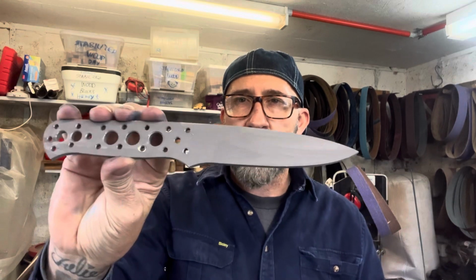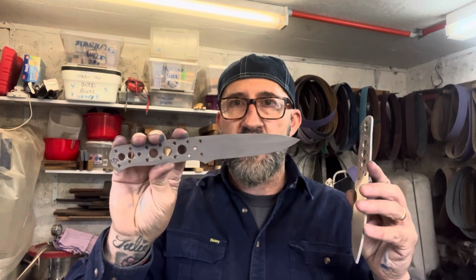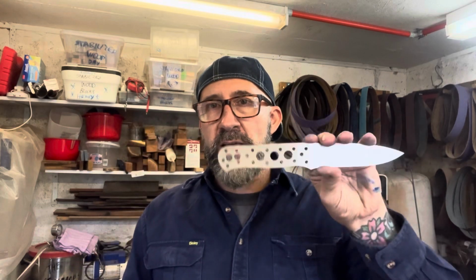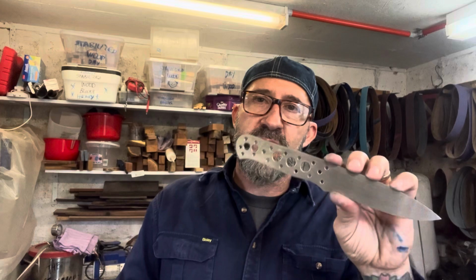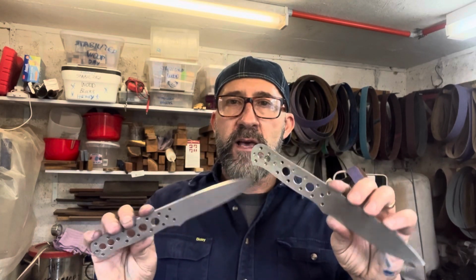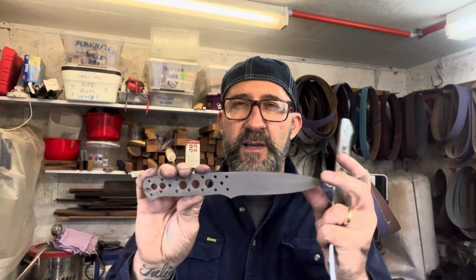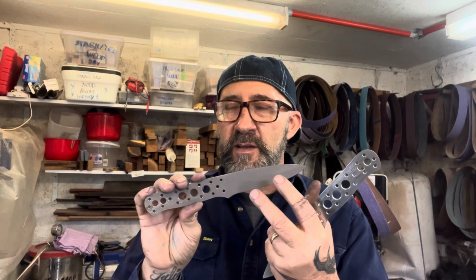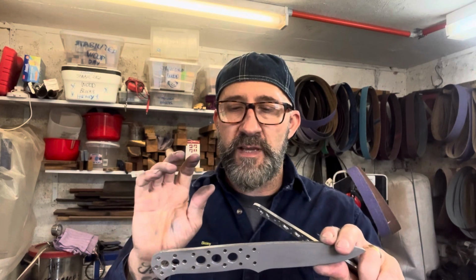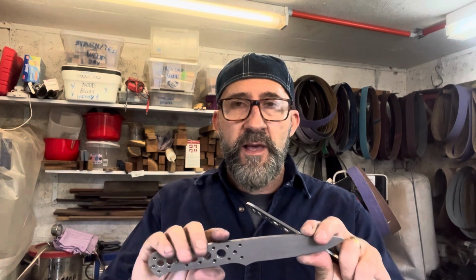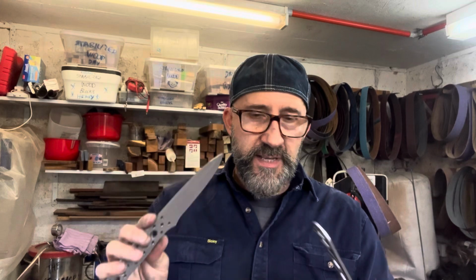I'm actually doing an O1 tool steel, but it's got a coating on it, ATP 64, which is like some kind of clay looking coating. Now I did try that on the stainless, and I found that because the O12 steel has a heat treat temp of around 800 degrees, whereas stainless steel you're looking at 1065, it's a big increase in heat, and it didn't seem to work. It seemed to go very black, and there was a lot of scale build up on there. So I'm assuming that it didn't work. It might have been my mistake. I don't know. I might have done something wrong, but I get good results on O1 and all the carbon steels, but on the stainless I stick to the foil.